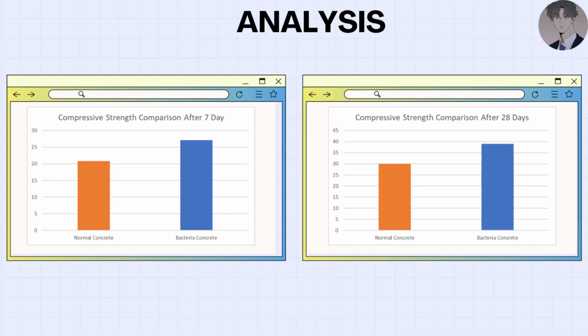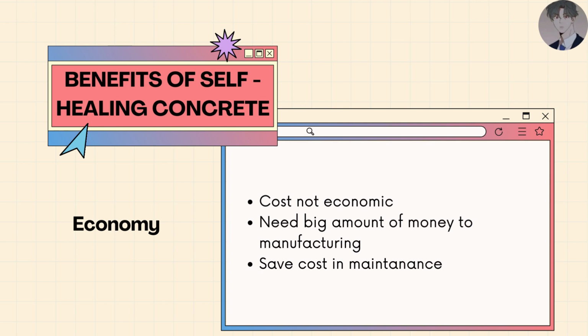We move on to the analysis of our test. First, we can see the compressive strength comparison after 7 days, which shows that bacterial concrete has higher early strength than normal concrete. And then we move on to the compressive strength comparison between bacterial and normal concrete after 28 days. Results show bacterial concrete also has higher strength than normal concrete because of the self-healing characteristics present in the bacterial concrete.